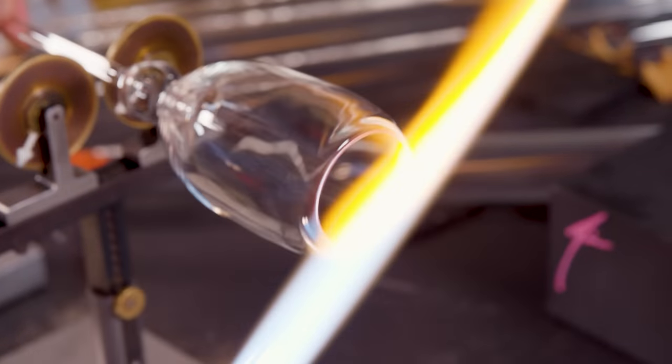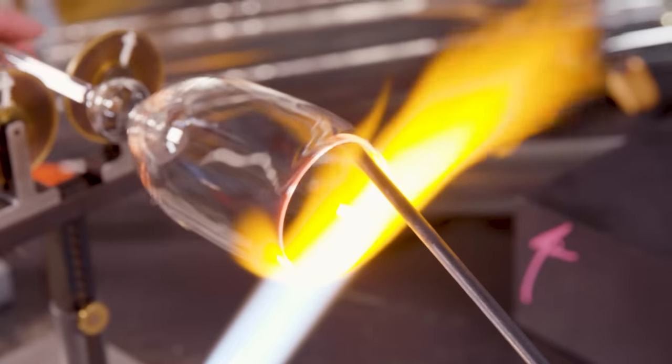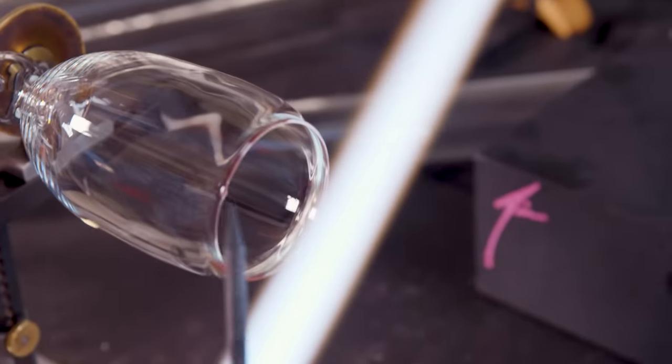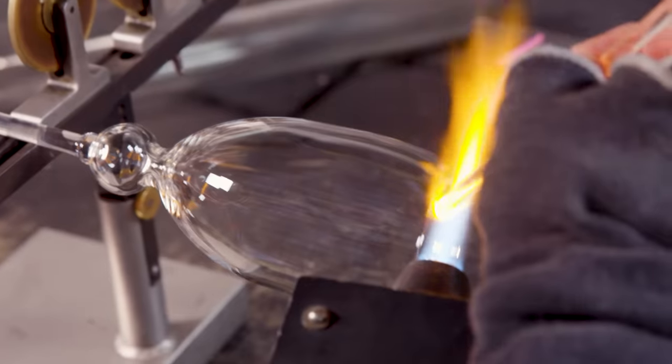So now where this is torn, there's going to be a little blip that I need to pick off of there. See it? Right there. That needs to come off. Otherwise, it'll just amplify as you make the lip or the foot.